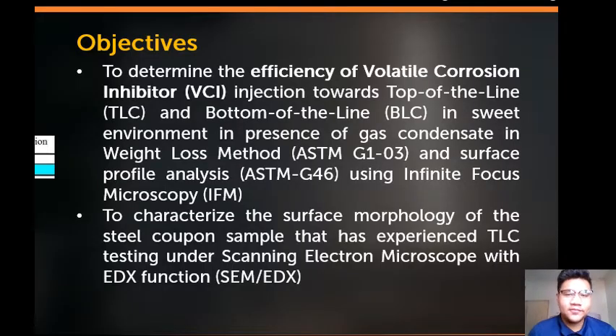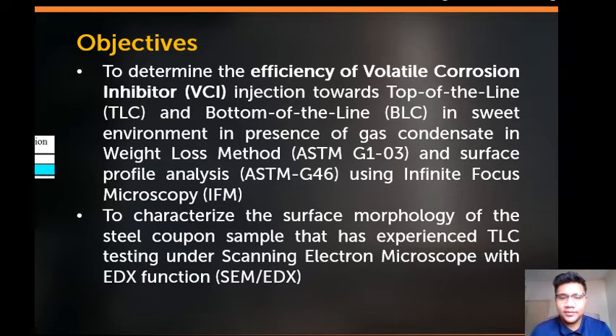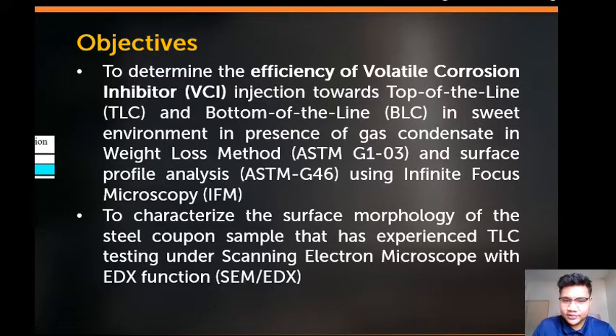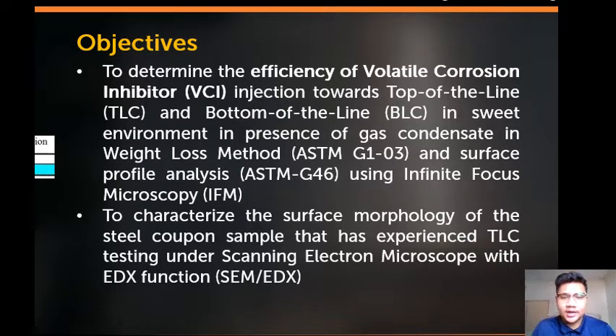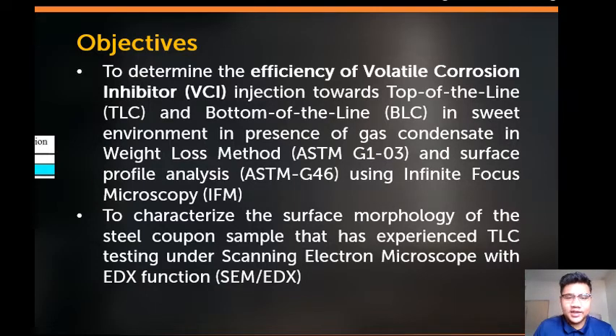The objective of this research is to determine the VCI efficiency in mitigating TLC and BLC. TLC is the top-of-the-line corrosion and BLC is the bottom-of-the-line corrosion in oil and gas pipeline. In order to have reliable results, this research will comply with the guidelines produced by the American Society for Testing and Materials, ASTM, which are ASTM G103 for preparing and cleaning, used to determine the uniform corrosion rate of the steel pipeline, and ASTM G46 for pitting analysis by means of using infinite focus microscopy.